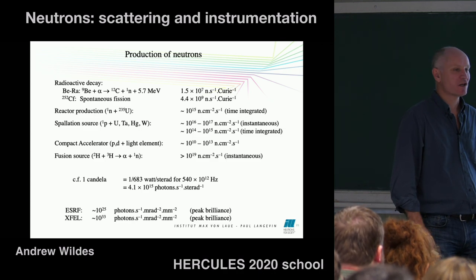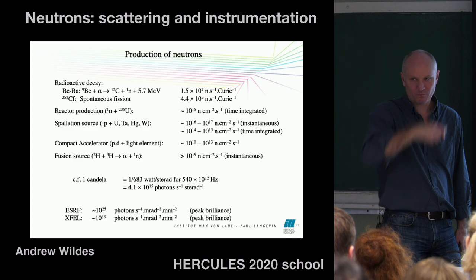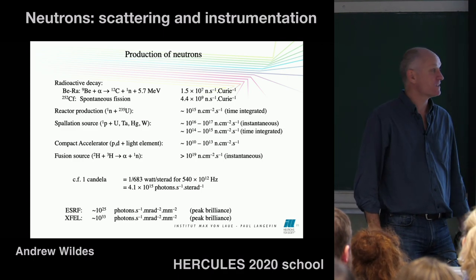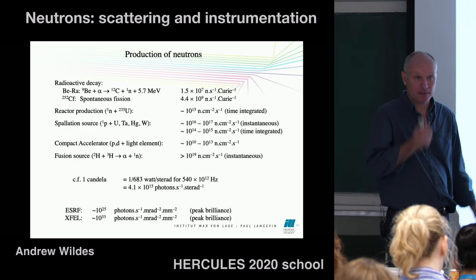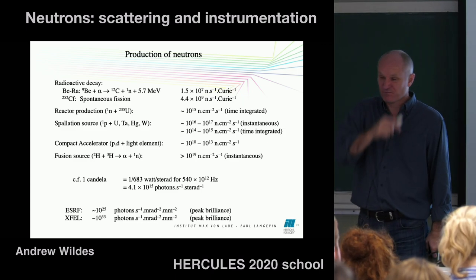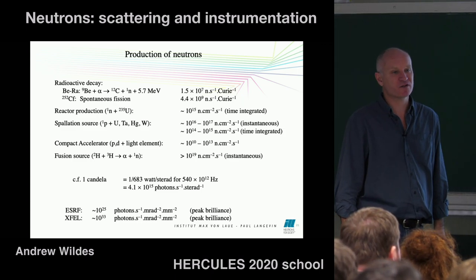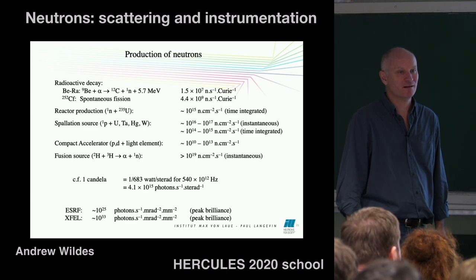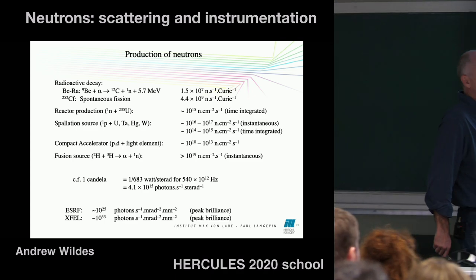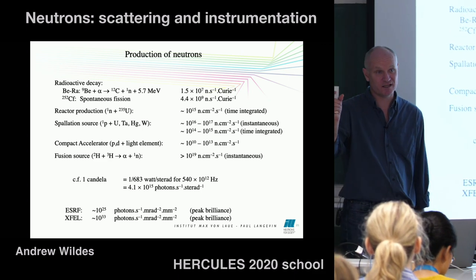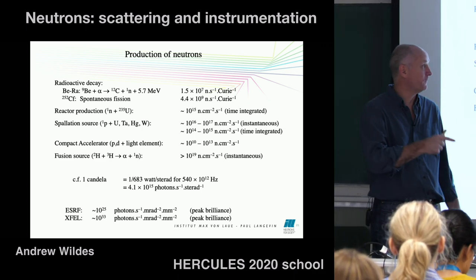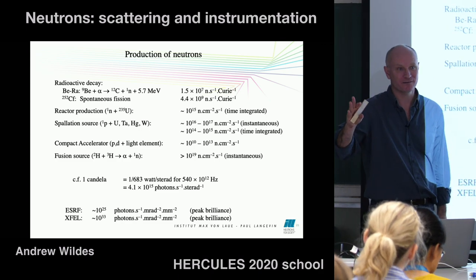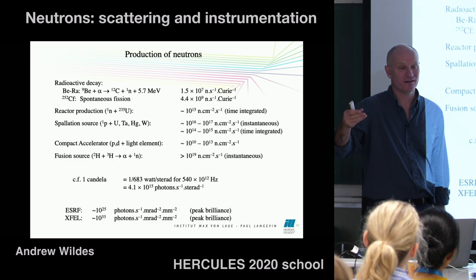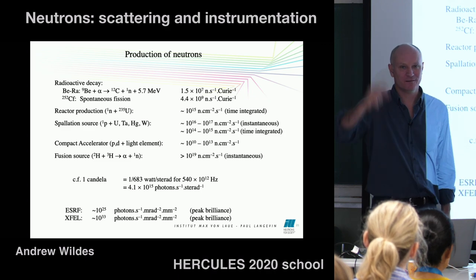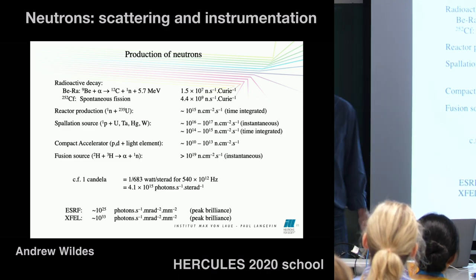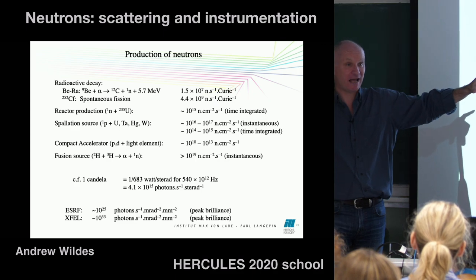Perhaps the best way I can describe that is by saying something like, if you start with this, that's what your source is producing. By the time you get into your detector, if you've got of the order of 10,000 counts a second, you have a very intense peak. So that's 10 to the 4. So you're going from 10 to the 15 to 10 to the 4 by the time you get into your detector. And that's strong. And often, you'll be down to a few counts per minute if you're looking at inelastic scattering. So you're potentially losing 15 orders of magnitude going from your source to when you eventually count a good neutron in your detector.